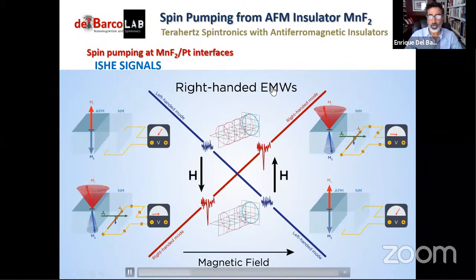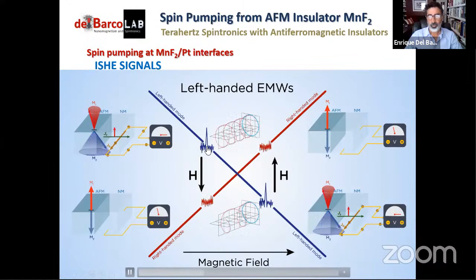We will hit the right-handed mode only at high frequency and low frequency. And this is gonna pump spins in a particular direction, and it's gonna generate a negative voltage in both cases, so a dip. And then if we go and use left-handed microwaves, we will only hit the left-handed mode, and this is going to pump spins in a different direction and generate a positive voltage instead of a negative voltage, resulting in a peak, right?